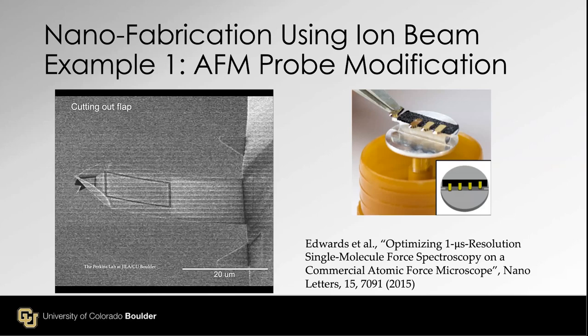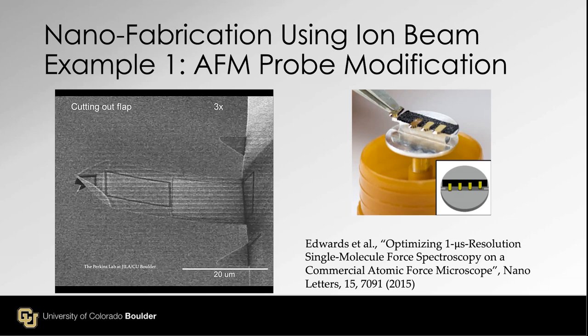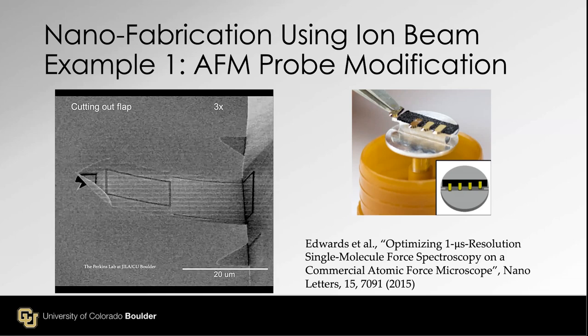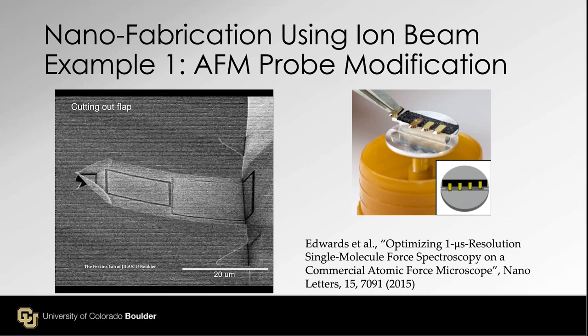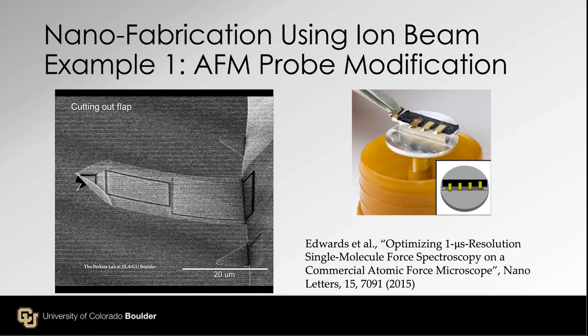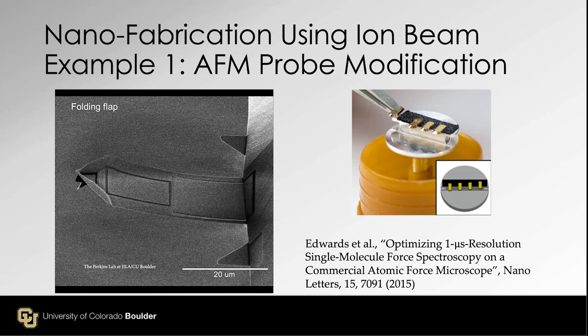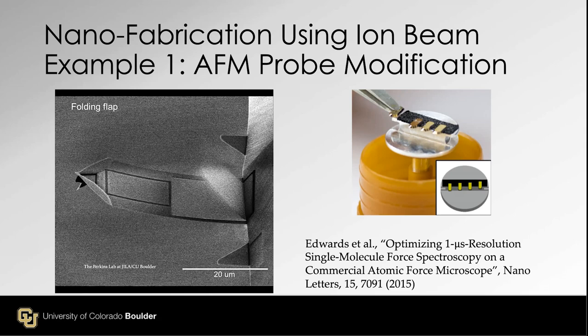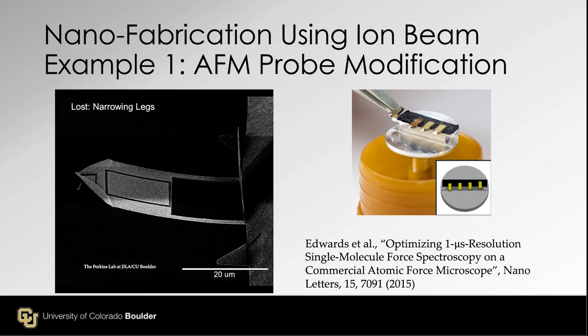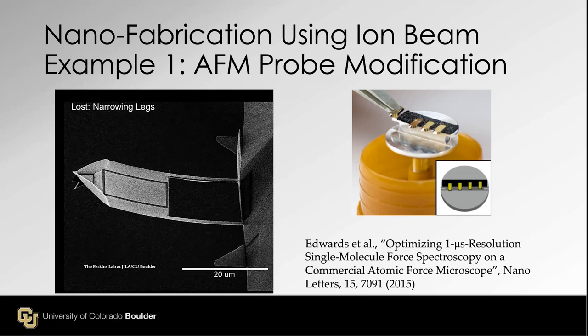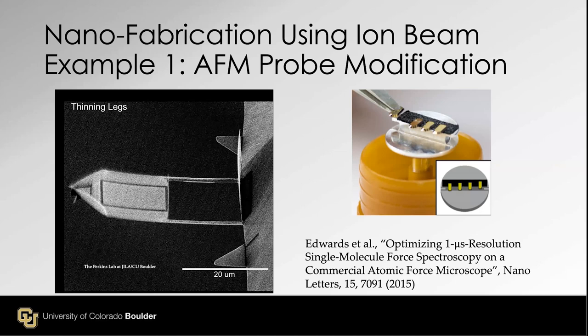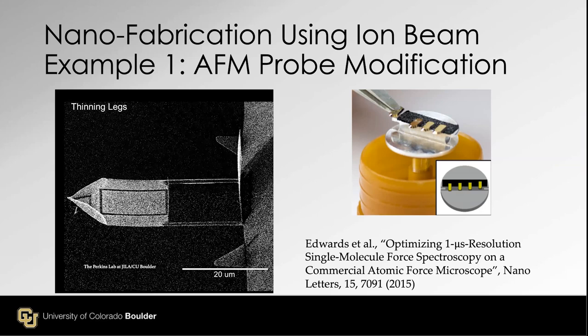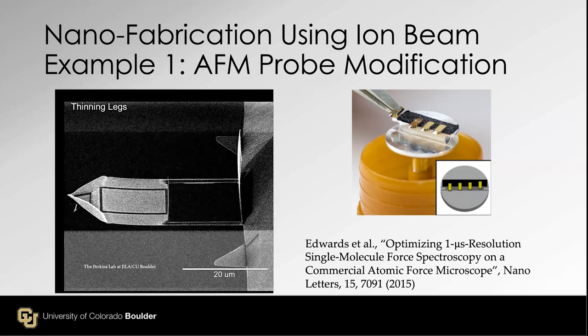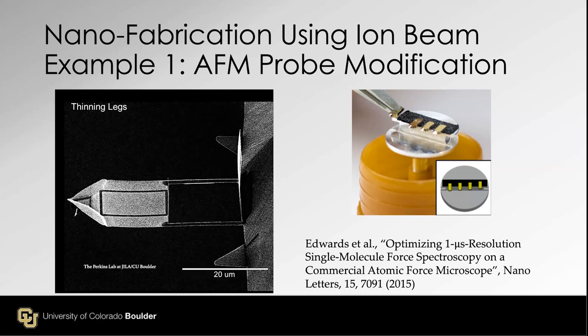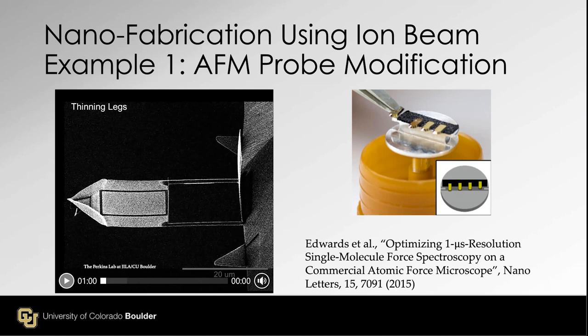So using the ion beam, they are making some cuts. This is the movie. They are trying to change the mechanical property of this cantilever by removing or adding some materials. So now it went up. They made a big hole in the middle of the cantilever to change the mechanical property, meaning the resonance frequency of this cantilever. And they are still making those legs thinner so that the cantilever works in the way they want. Okay, this is in the field of biomedical. So this is one example.